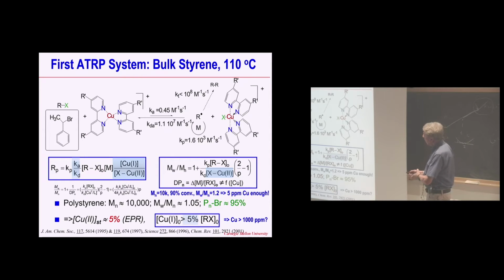So why do you need copper? You need copper to send this radical from propagating stage to a dormant state fast enough. And dispersity here shows that this depends on a reciprocal concentration of copper 2. So I need a certain concentration of copper 2 in order to have polymers with low dispersity. For example, if I want to make a polystyrene 10,000 at 90% conversion, dispersity 1.2, 5 ppm of copper is enough. But if you would run this reaction at 5 ppm, a little bit of termination will completely stop the reaction. So you need to solve a problem like that.